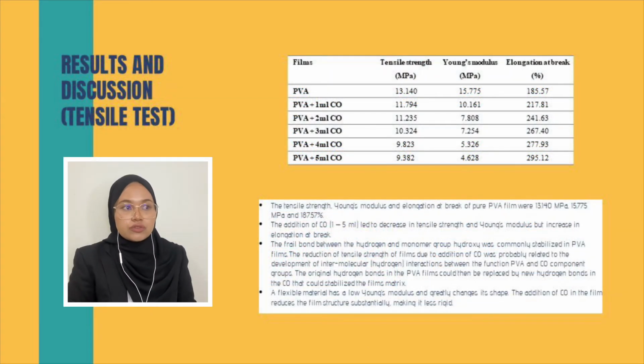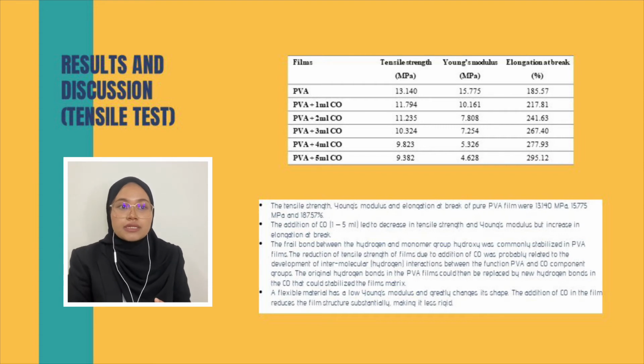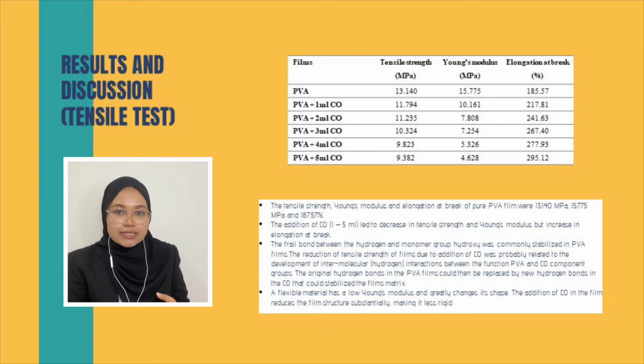And now, we will go through the result and discussion of the tensile strength. For the pure PVA films, the tensile strength is 13.14 megapascal, Young's modulus is 15.775 megapascal, and the elongation at break is 185.57%. The addition of CO from 1 to 5 ml led to a decrease in tensile strength and Young's modulus, but an increase in the elongation at break.